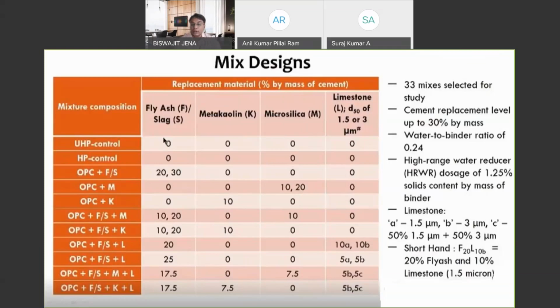So if you have 5% of superplasticizer, you mix it with all the available water and you pour it in, and you are going to have failure in that case, because you should not mix it in simultaneously. So in that case, nothing is going to happen. So I'll show you the different mixing methods that need to be changed if you want to design this type of ultra high performance concrete.